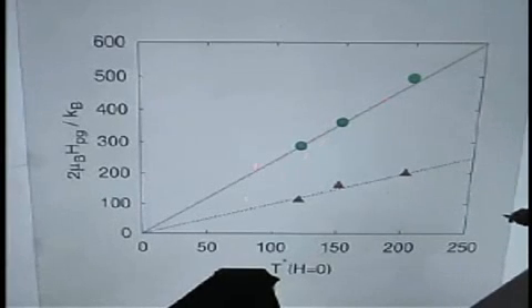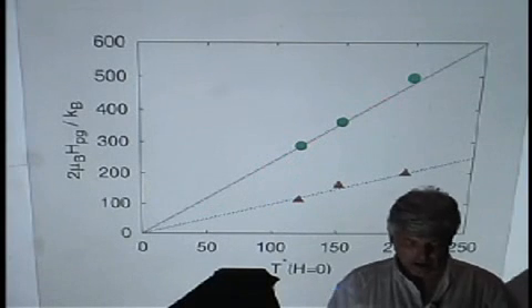There is a factor of 2 essentially in the slope of this curve. We get a linear coefficient, but we don't get the slope of one. We have an explanation for this difference, which is essentially related to this entropy factor, the log factor I was showing before.